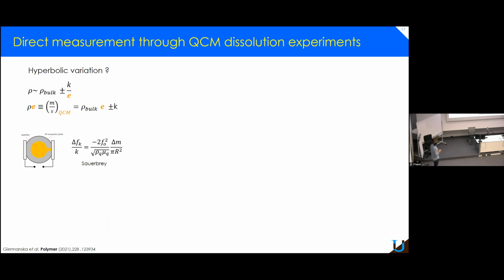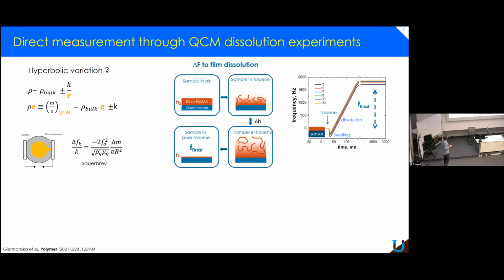So here, this is typical. If it's a hyperbolic variation, the density of the thin films is somehow a function of the bulk density plus or minus something over the thickness. So if you multiply the thickness on both sides, what you get actually is the mass per unit surface. And this is something that we can normally measure using QCM, the quartz crystal microbalance. So it's exactly what we did. The way we did the experiment is the following.